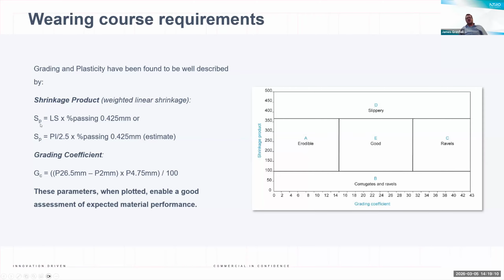0.425 millimeter sieve, or as an estimate, the plasticity index divided by 2.5, which will give us a good indication of the linear shrinkage, again multiplied by that passing 0.425 sieve. So that's going to give us the number on the y-axis, and our grading coefficient, which is essentially an exciting equation made up of different amounts passing different sieve sizes. So percentage passing the 26.5 millimeter sieve minus the percentage passing the 2 millimeter sieve, all multiplied by the percentage passing the 4.75 millimeter sieve divided by 100, which will give us a grading coefficient.